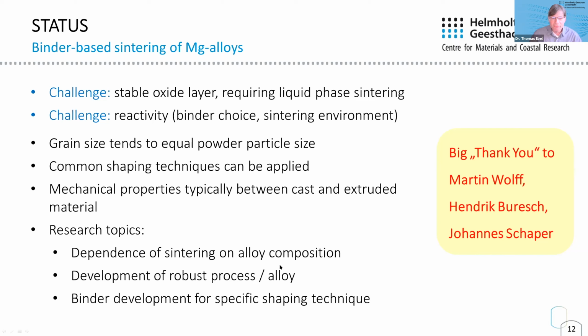Then we would like to develop a robust process, or also a robust alloy, which is more tolerant against variations of the sintering process. And for the specific shaping technique, we need dedicated binders. So we are also doing binder development and using binder components which do not react with the magnesium in such a way that they hinder sintering.